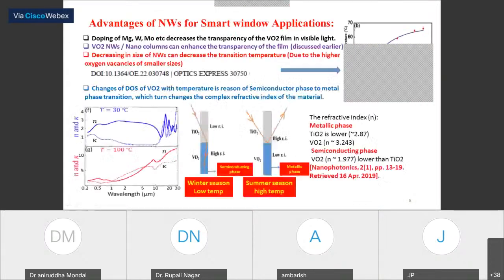This is one kind of heterostructure nanowire material, which can be used for high refractive index and low refractive index. The idea was that if we use this kind of anti-reflection coating, with the low refractive index at the top and the high refractive index at the bottom, it can be used to let infrared rays enter the room when used as an anti-reflection coating on the smart window of the room. So it can be used to warm the inside of the room in the winter season.